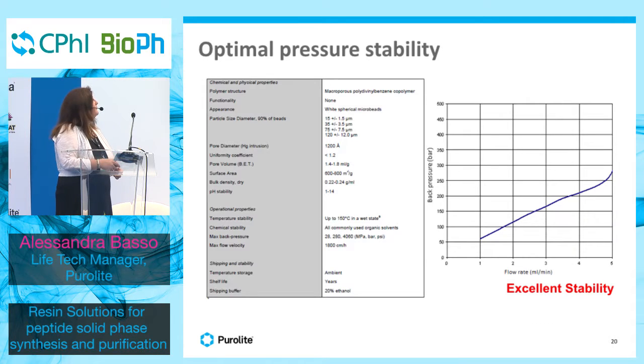The resins are also very stable to pressure and chemically stable. In that graph, I show the back pressure of a 15 micron product, and you can get pressure up to 200 bars. You don't need 200 bars in a typical process with 15 micron, but the resin is very, very good and stable.